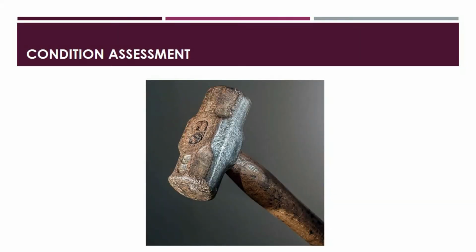Now, the assessment process begins with a simple visual evaluation of the wood poles, followed by basic physical testing such as poking test for surface condition and hammer test for internal decay indications. Many utilities use this method largely as a safety process for alignment to follow before climbing.